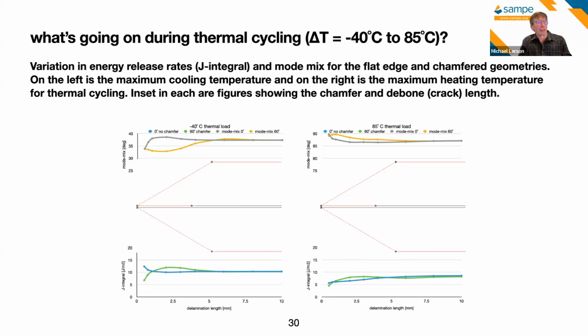Something else we found that was kind of interesting around this chamfering is looking at the chamfered and unchamfered, which are shown in the center of this figure, with plots above the mode mixity, and that refers to the relative proportion of how much is shear versus how much is tending to open the crack, which are different for the chamfered and unchamfered cases significantly. So we're changing the failure mode. So something to be aware of is if you do chamfer, you are using an adhesive that then is subject, in the cold side of the thermal cycling, to a different sort of mode loading than if you're not chamfering, which again, not unexpected, but at least you can get some idea.